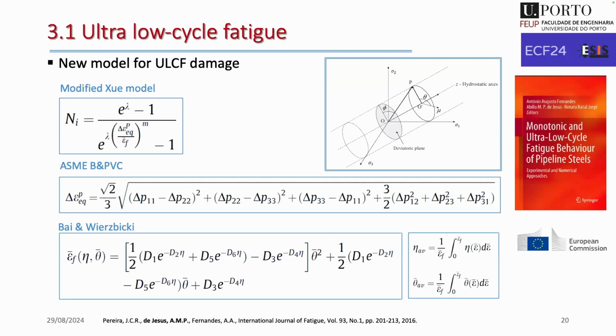So we have played with, let's say, continuous damage mechanics coupled models to address the material damaging in this fatigue regime, which is affordable because we are talking of 100 cycles, more or less. So it's possible to integrate the equations for that duration. But today I bring a simpler model, just to make it easier to demonstrate the background idea of the modeling in this fatigue regime. In this case, I'm talking of an uncoupled model that relies on a very precise cyclic plasticity modeling. This is mandatory, otherwise we will fail in our predictions.